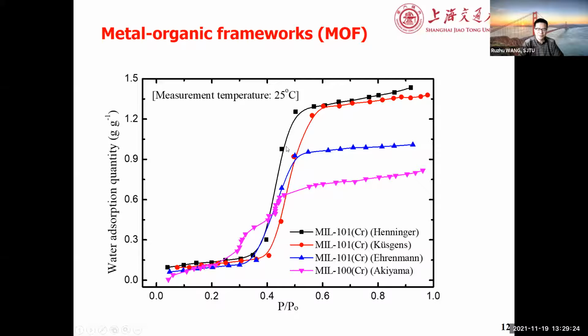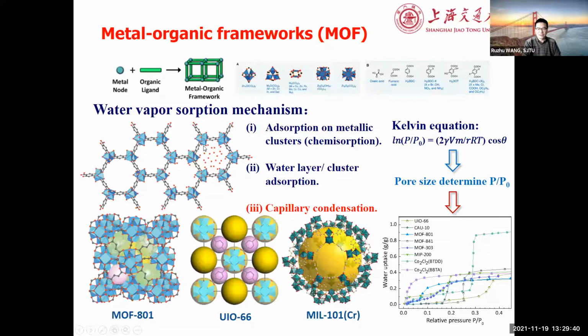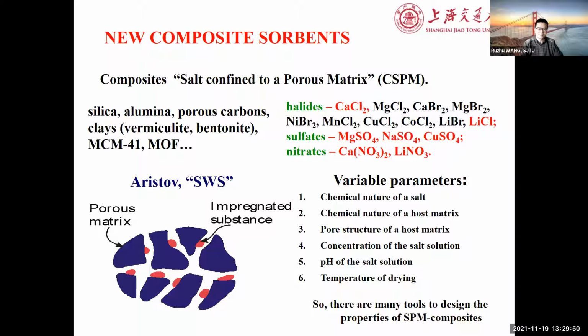So you could see the jump with a very small relative pressure or relative humidity change, you get a big jump, more than 1 gram per gram of adsorbent. This is for the adsorption of moisture from the air. And there are more developments for the MOFs and some theoretical analysis of their performance. Now we also developed composites confined in a porous matrix, because lithium chloride or calcium chloride have a very big absorption capacity for moisture, going from strong liquid to weak liquid.